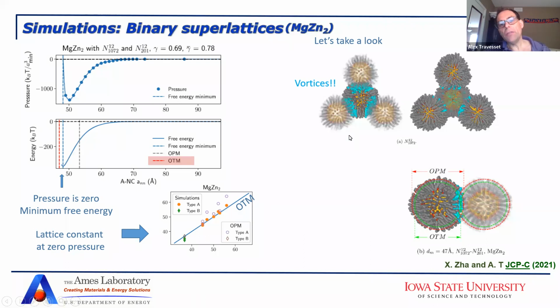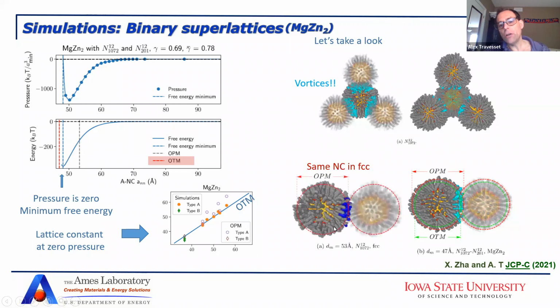By the way, if I take an FCC lattice formed by these nanoparticles, the separation looks like this. And you can see here how the hard sphere describes very well where the nanoparticles are. So this is another verification of the prediction of the OTM. We see that for coordination 4, which is magnesium zinc 2, they form vortices. And for coordination of 12, which is FCC, they behave as hard spheres. So this is another demonstration, using numerical simulations, that the predictions of the OTM are actually satisfied.